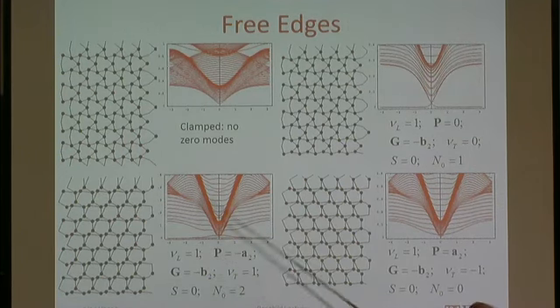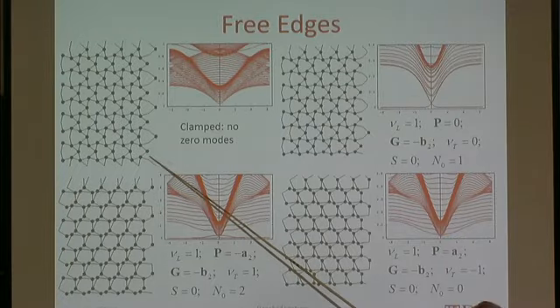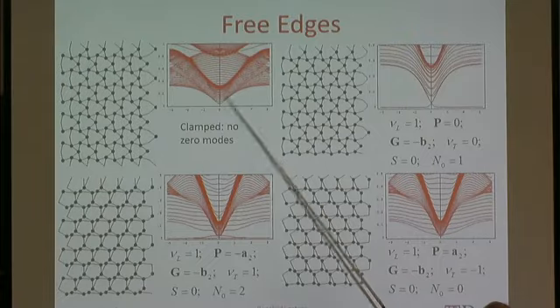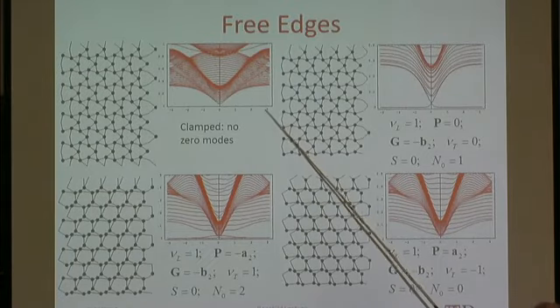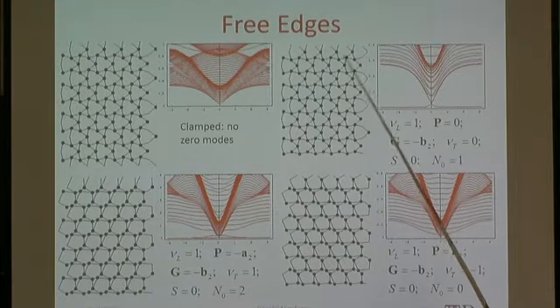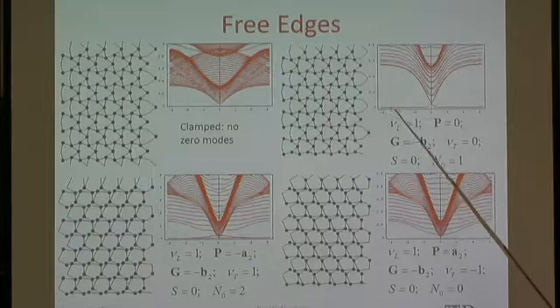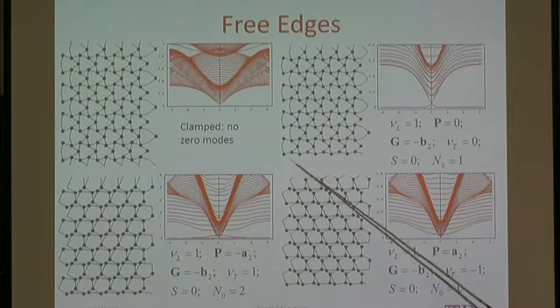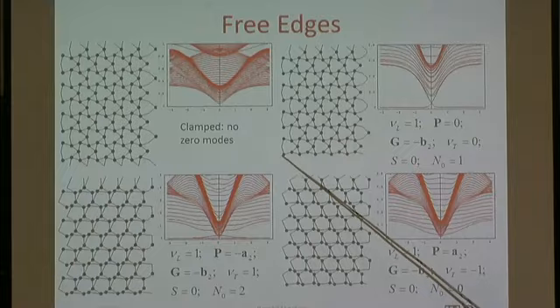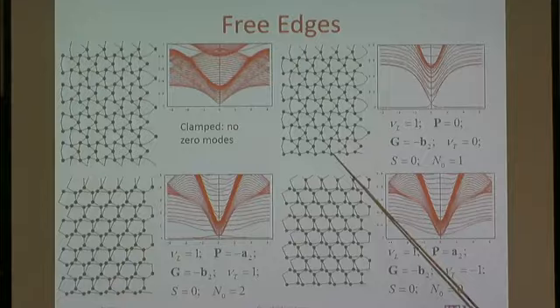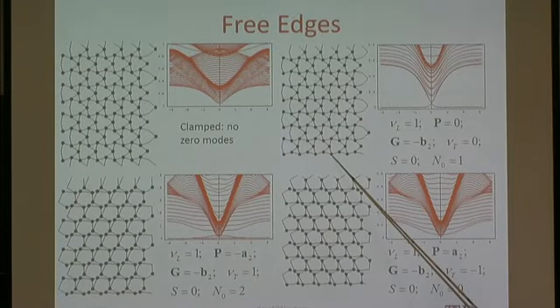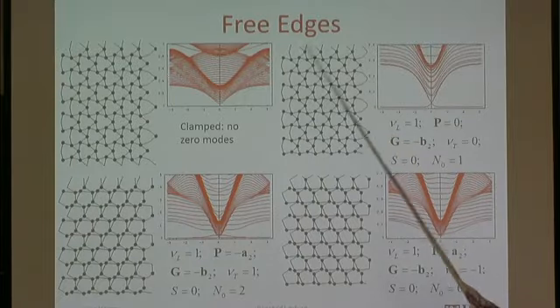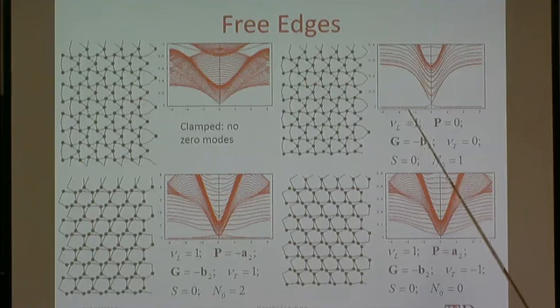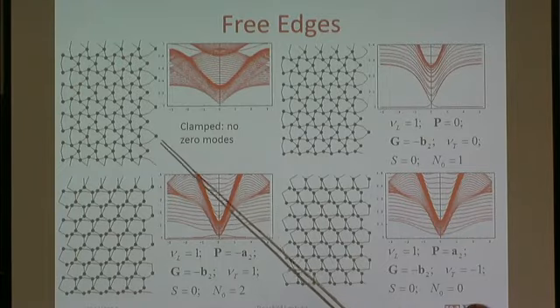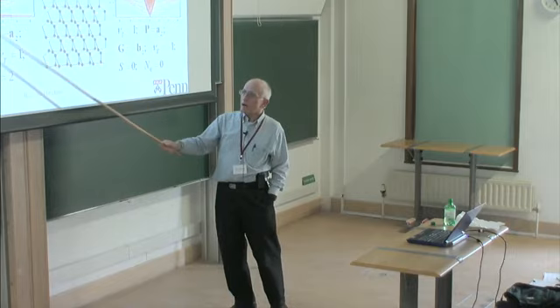So here are the numerical calculations. This is the Kagome lattice clamped at both ends. This is a spectrum of the finite strip. There are no modes of zero energy down here. Here, I clamp the top, and I look at the zero modes, and there's one zero mode for every wave number along the surface Brillouin zone associated with this surface. Now, this is clamped up here, but these things are sufficiently twisted that the surface states are localized, and it doesn't feel that. So up here, I have a state of self-stress that I'm not looking at, and I get this. Now, let's look at this state. That was the one which was obtained by rotating in the opposite direction.